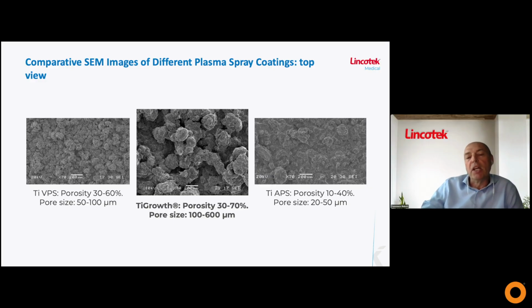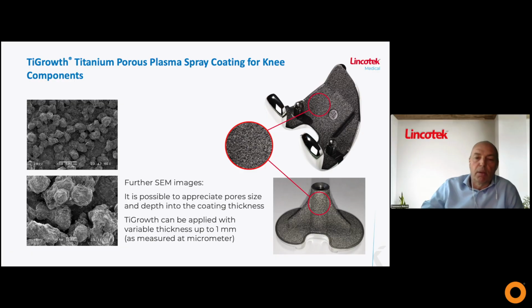The center image is really TiGrowth, at the same magnification as the other two. You start to understand the pore size, which is on a different scale, with a few hundred microns in both depth and width. Here you have different magnifications, and you have an opportunity to appreciate the size of the pores and the thickness of this type of coating that can be used on both femoral or tibial plates in knee joints.